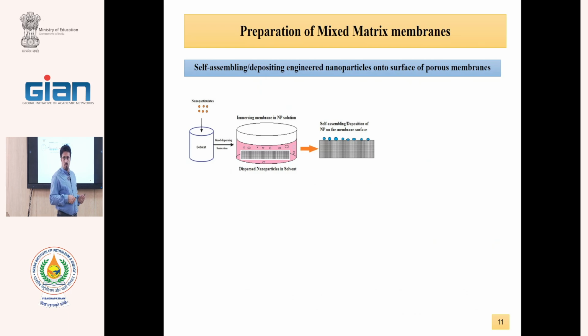this nanoparticle solution and kept for 1 hour. In this case, nanoparticles deposit and self-assemble on the membrane surface. And the membrane surface is important because the separation layer is the top surface. In this case, we have high efficiency and the contact angle reduces rapidly. Okay?